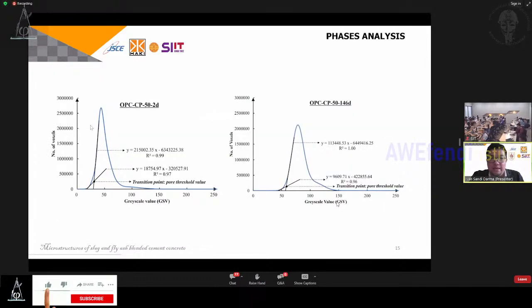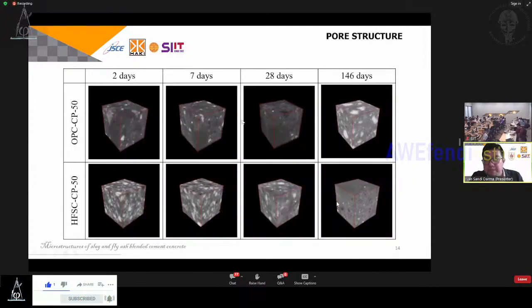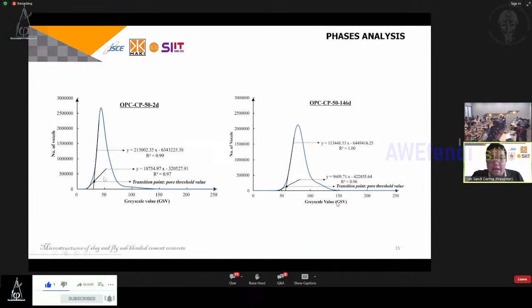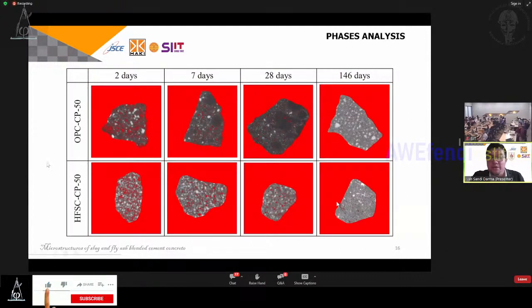And then for the pore structure, using the same specimen and same VOI, I have a histogram here, and I try thresholding to separate between solid and void items. As you can see here, the red one means void, and the gray up to the white means solid. As you can see here, of course, at maybe 2 days or 1 up to 3 days, we will have a very high porosity in both specimens, both OPC and also fly ash.